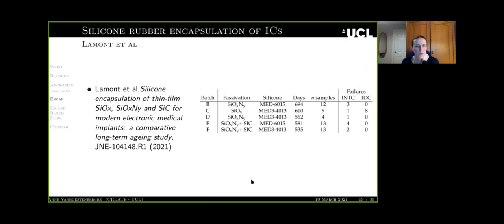The study that I'm going to report on today compared five different batches. What you're going to see here is that we have three different types of passivation: silicon oxynitride, silicon oxide, or silicon oxynitride with a silicon carbide, and two different silicone rubbers. As you can tell by the names of the batches, there was a batch A, but there was a fabrication failure, so we have no results to report on batch A. The study ran for a little bit more than a couple of years, so we have data up to 694 days.